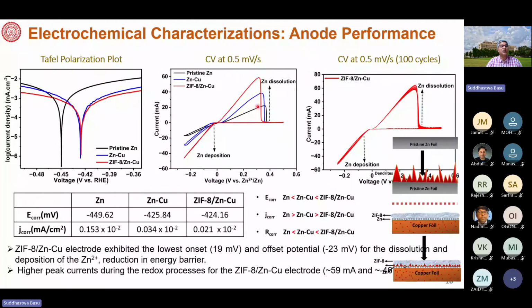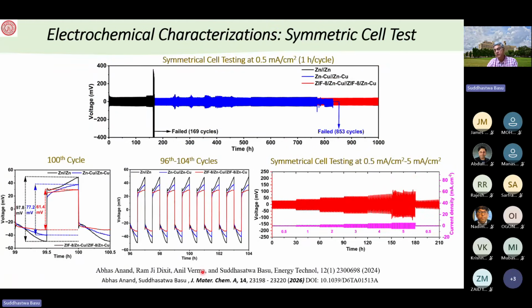One is kind of ash color, one is blue color copper zinc, and compared to that zinc, we have a higher current where we have ZIF8, we have a lower onset potential, this red one, notice. And when we have many cycles, it shows that it goes through many cycles and there's no deterioration for the ZIF8 zinc copper anode or negative electrode, so it works excellent. So we have E corr highest at minus 424.16, because it's a minus, that's how 424 is the highest, and the current is lowest, as I showed you before, and so that is how the corrosion is lowest for the ZIF8 zinc copper electrode. Okay, so this is what we have done, and then we run the cell.